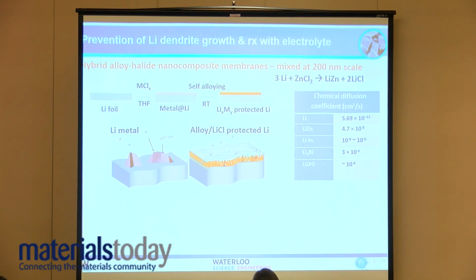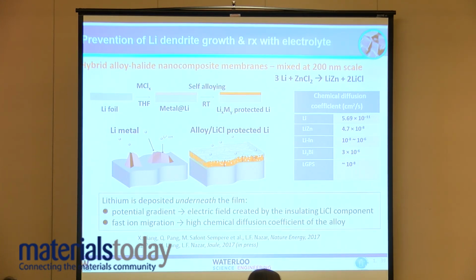So the orange is the alloy, and the pale blue that you can sort of see in the interstitial areas here is the halide. And that gives it a resistivity of about 10 to the 4th ohm centimeters, which is enough to drive the lithium underneath the film and deposit under the film. So now there's no lithium on top of the film available for dendrite growth. So it established that the resistivity conveyed by the halide in the film is enough to create the electric field, and the alloy itself provides the conduit for the lithium diffusion through the alloy itself.